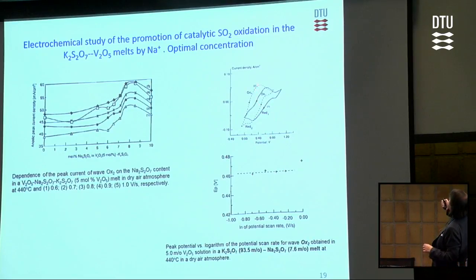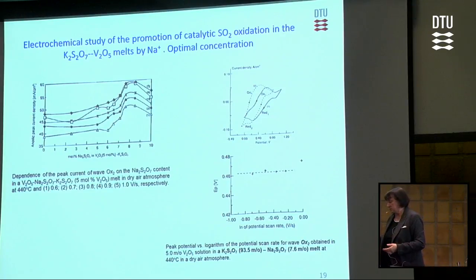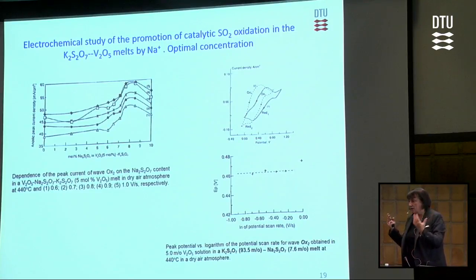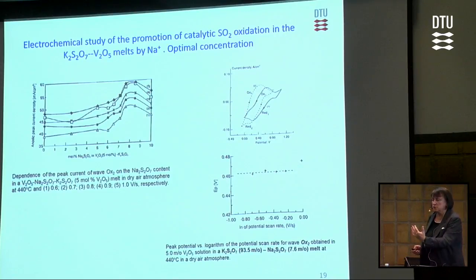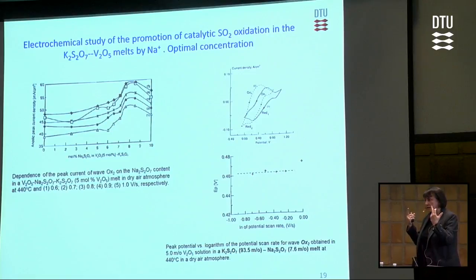Now, we add sodium again. You can see, this is the slowest step, you can see the peak potential when we add some sodium is independent of potential scan rates. That's the sign of a fast reaction. So, you see how easy it can be done, how easy you can see the effect. Just imagine you're doing it with a real catalyst and chemically.